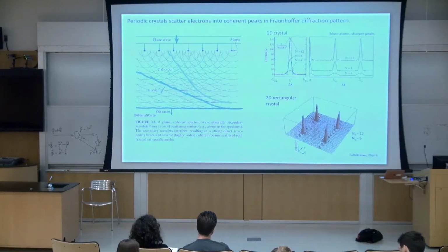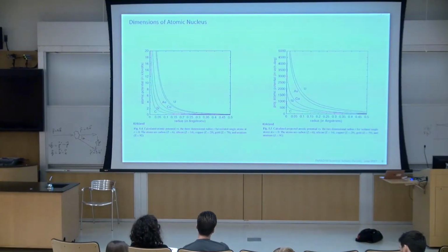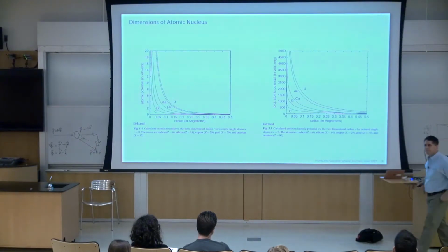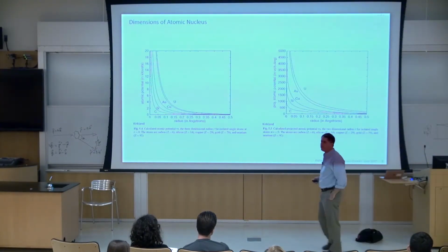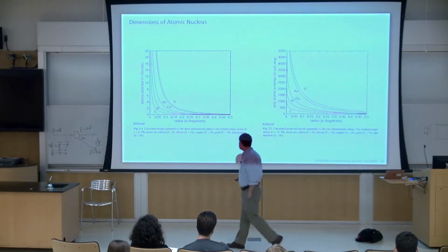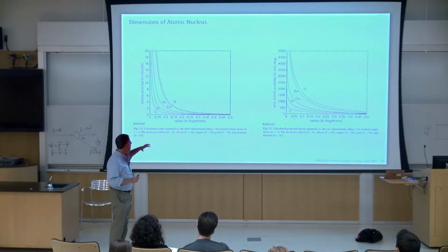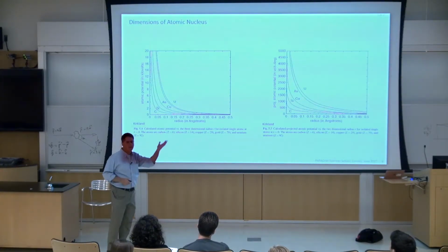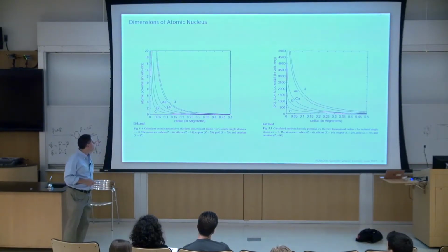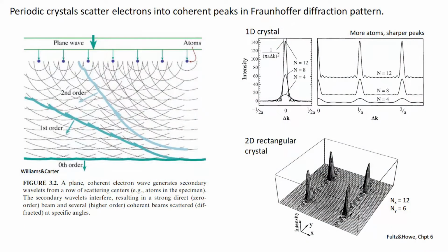And that means that if I look at scattering at large angles, it's less likely to happen than at small angles. And eventually I get to big enough angles and it can fall off pretty quickly. To first approximation, if I'm looking at low order scattering, I'm just going to treat that as a constant. And then if I worry about big angles, obviously it's dropped off a lot. But if I treat it as a constant, it's a delta function. Math is easy.